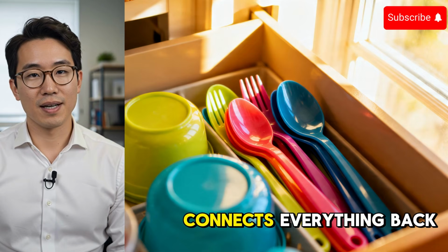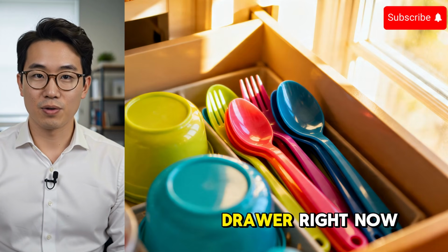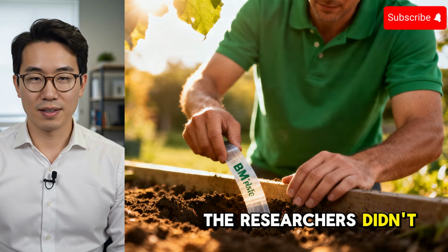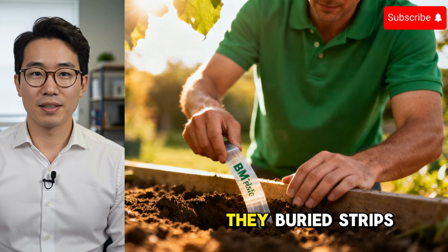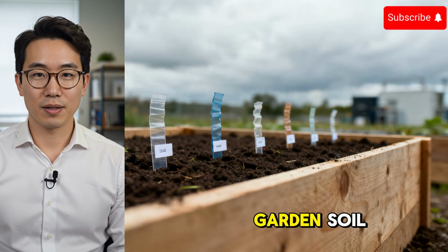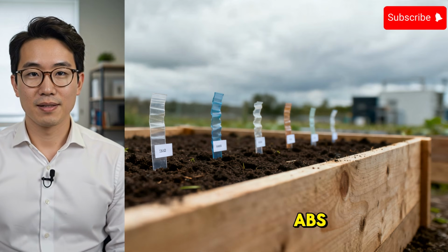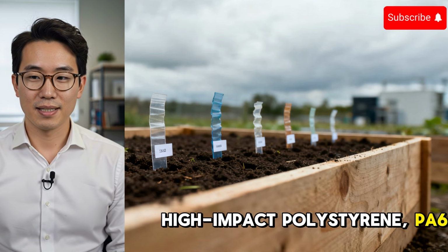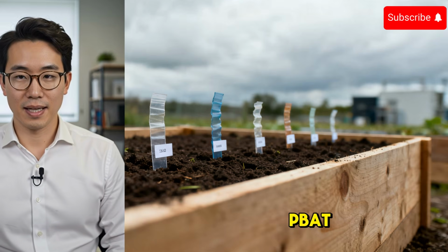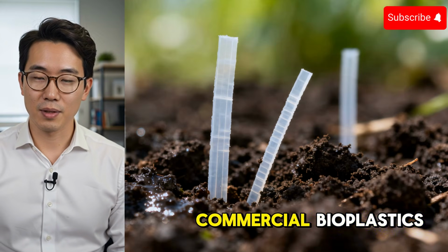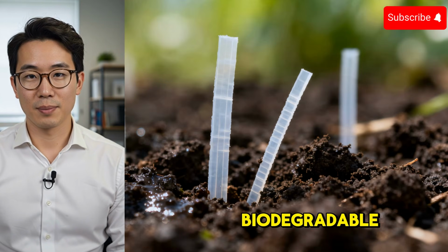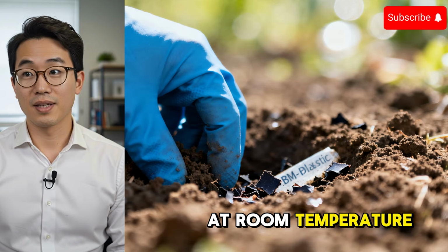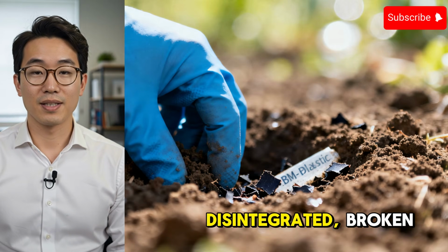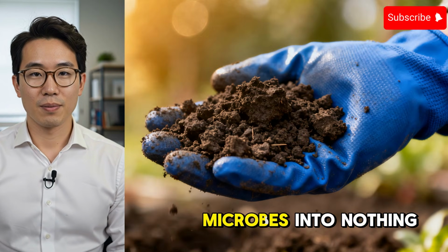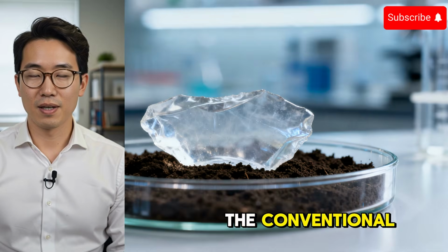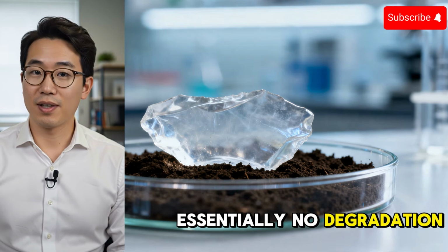Now here's the part that connects everything back to the plastic sitting in your kitchen drawer right now. The researchers didn't stop at strength and heat resistance. They buried strips of BM plastic in ordinary garden soil, alongside strips of ABS, high-impact polystyrene, PA66, PMMA, PLA, and PBAT, the last two being existing commercial bioplastics already marketed as biodegradable. After 50 days at room temperature, the BM plastic had completely disintegrated, broken down by ordinary soil microbes into nothing detectable. The conventional petroleum plastics showed essentially no degradation at all.